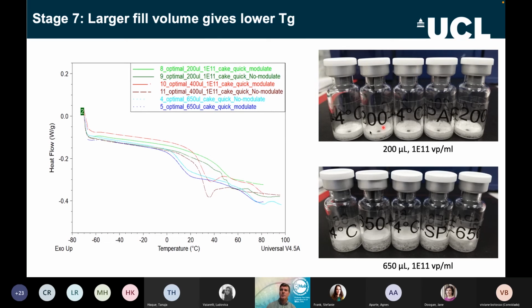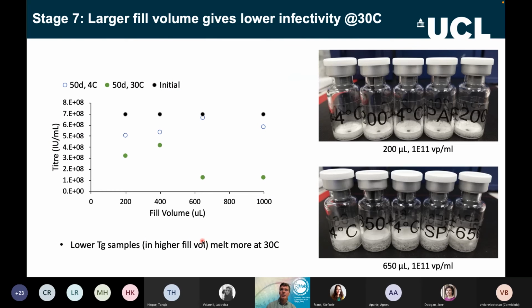We took those samples out and went back to measuring the glass transition, and this is the calorimetry work that shows where the glass transition is, the transition point between an amorphous state and melting. You can see the small fill volumes in green have a much higher glass transition in the solid phase, of around 40 degrees, largely due to sucrose, than the higher fill volumes, where the glass transition comes down really low. This might be why we get problems, because this can melt quite easily, causing meltbacks. It's less stable. So that could be one reason behind it, the lower Tg.